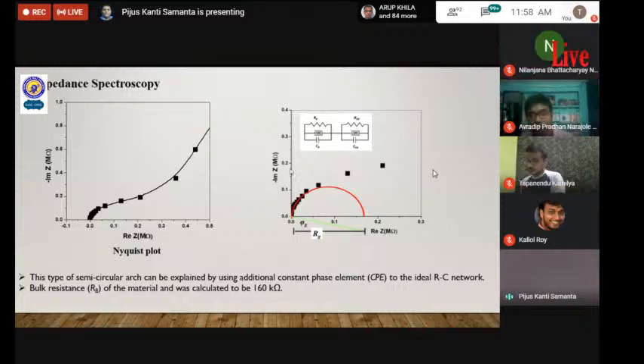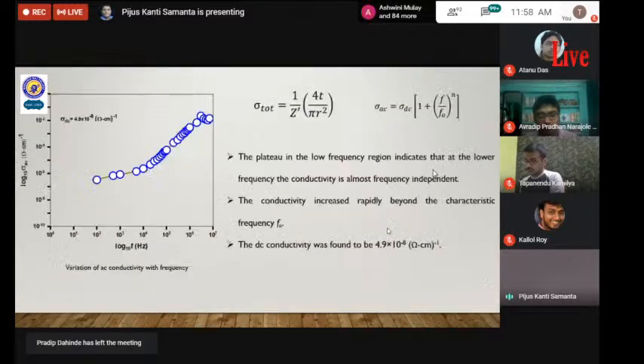And from this semicircular arc, we can find the bulk resistance of the material. That is from the bulk contribution. That was about 160 kilo ohm. And ideally, this circle should be an ideal circle centered at this zero axis. But we see a depression of the curve due to non-Debye type of relaxation process that can be incorporated by using an additional constant phase element into the equivalent RC network of the dielectric system. So this figure shows the variation of the AC conductivity with frequency.